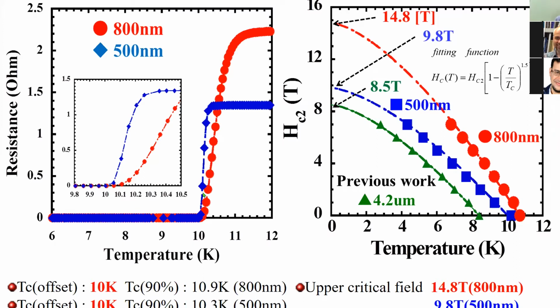So anyway, we can observe this little bit thin layer. This is not thin from the point of surface science, but from material science, less than 1 micron is very thin. The most successfully and reproducibly observed superconductivity, relatively high temperature above 10 Kelvin, comes from relatively thin material.